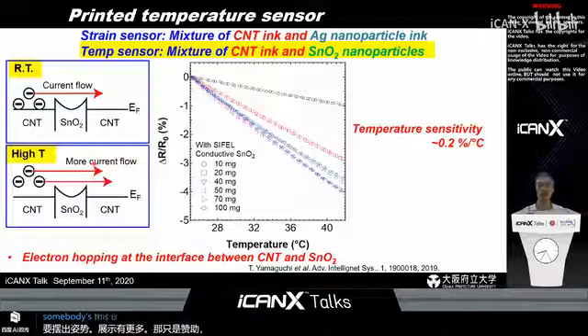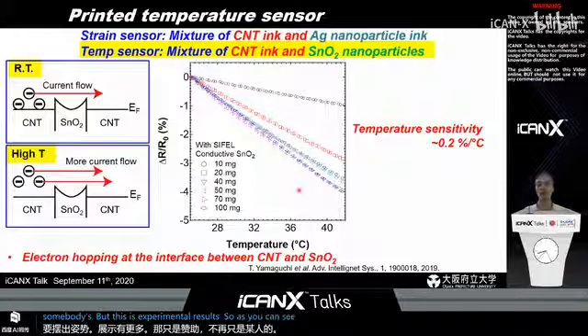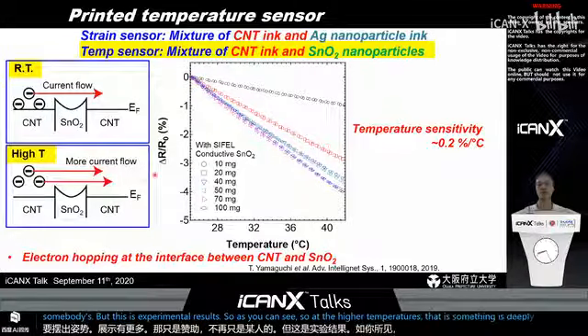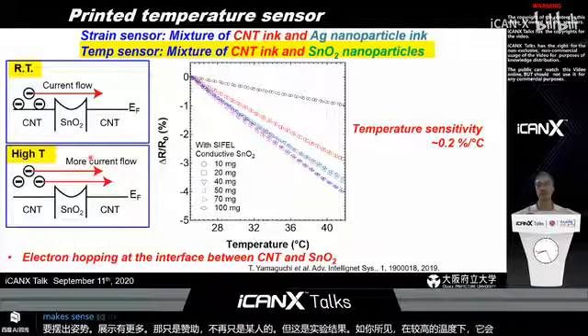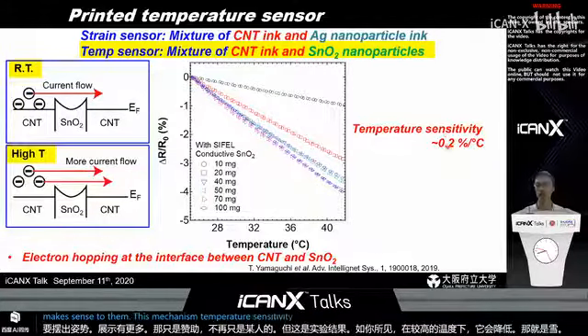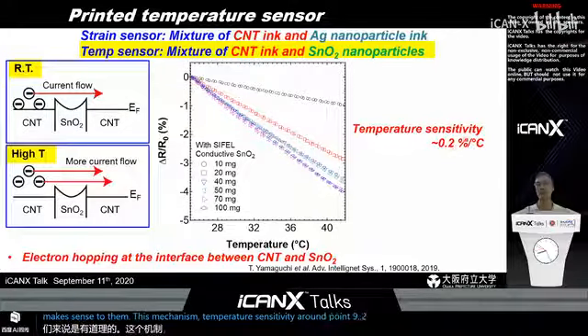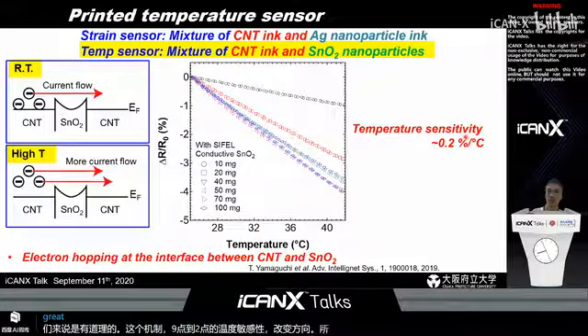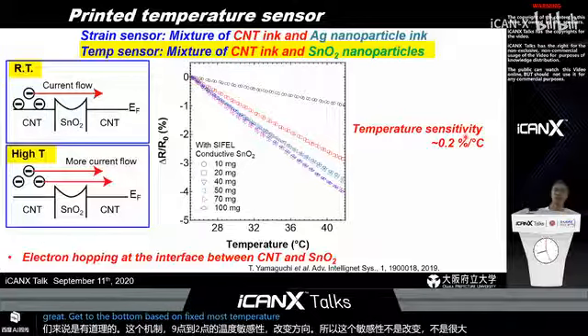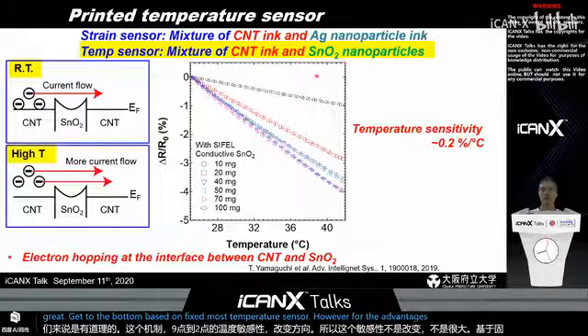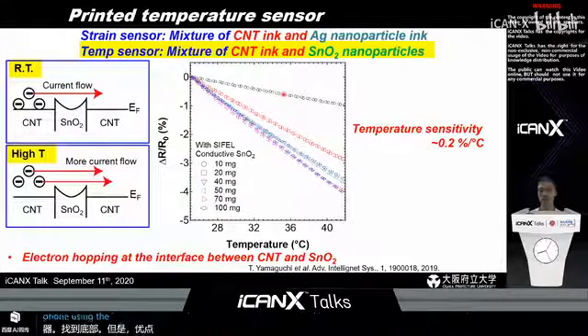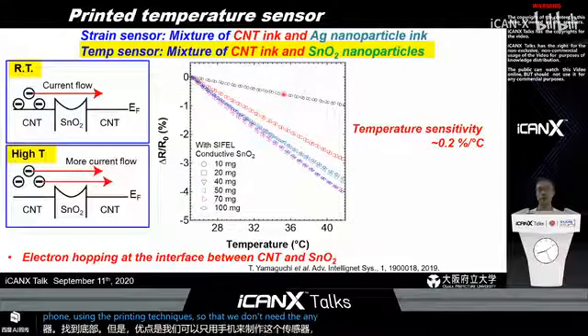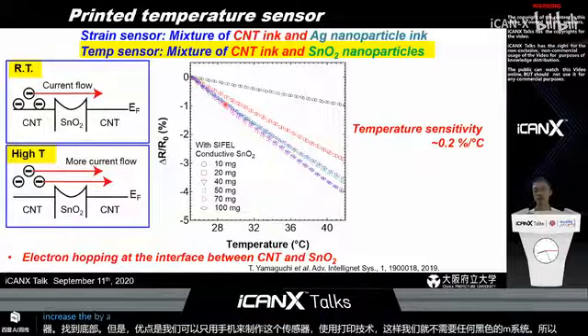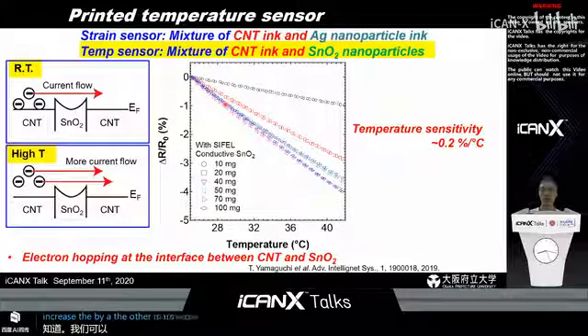So these are the experimental results. As you can see, at a higher temperature, the resistance is decreased. That makes sense with this mechanism. And temperature sensitivity is around 0.2% resistance change per degree C. This sensitivity is actually not great compared to the platinum-based flexible temperature sensor. However, the good advantage is we can make this sensor using only printing techniques, so we don't need any vacuum system to make this sensor. We can realize mass production without increasing device cost.